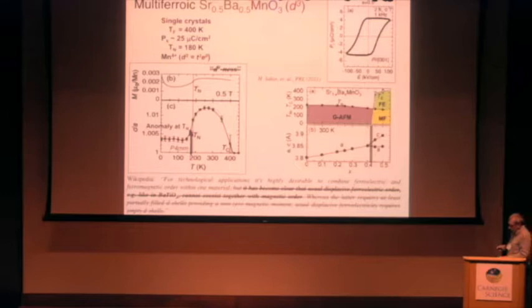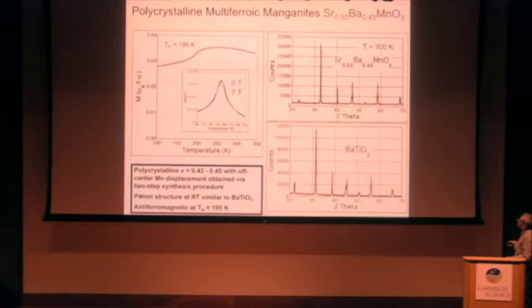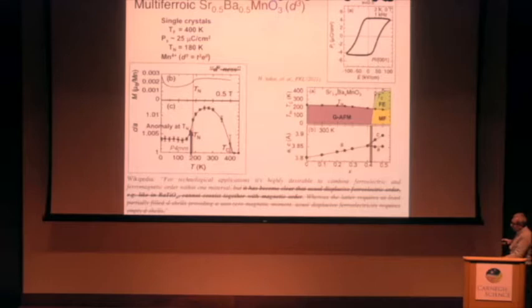We attempted to make them also, and a year later, we finally made them, even though we tried for many years earlier. We achieved only very small range of solubility for pure strontium-barium system. It's antiferromagnetic, completely not changing in the field, diffracts the same like barium titanate, except peaks are shifted because this has smaller lattice constant.